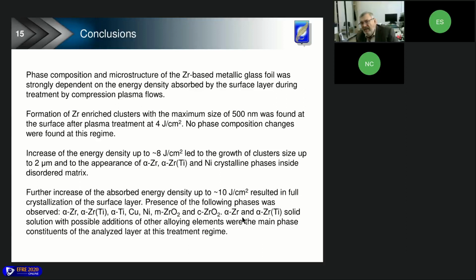And one more important moment. The structure of the metallic glass, as you can see, was strongly dependent on the energy density absorbed by the surface layer. So, compression plasma flows can be used for testing such a gentle material as metallic glasses, to test its stability under plasma or temperature impact.